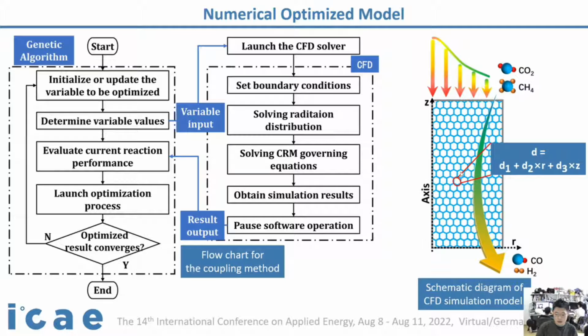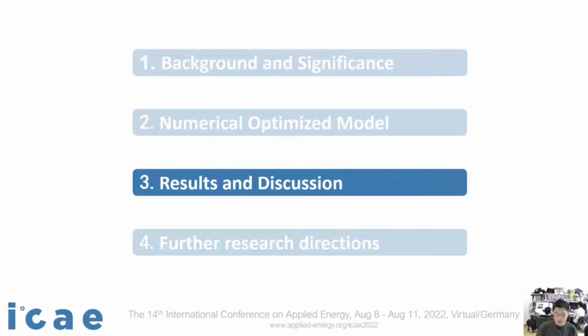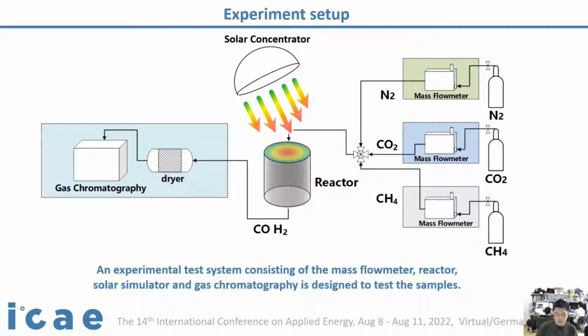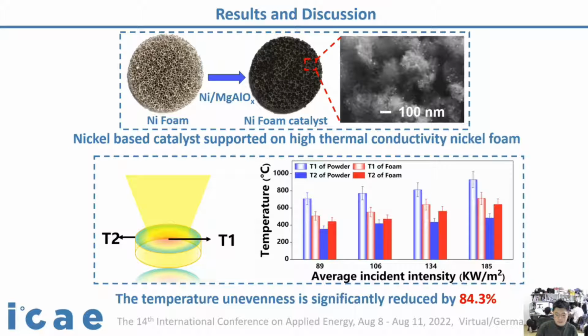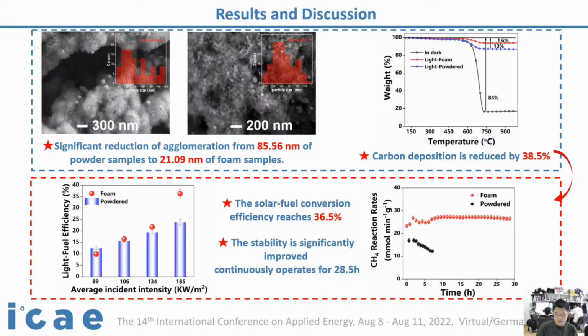The next comes the third part, results and discussion. We first built an experimental test system consisting of the mass flow meter, reactor, solar simulator, and gas chromatography to test the samples. Then we got the nickel-based catalyst supported on the nickel foam. Because of the high thermal conductivity of the foam, the temperature unevenness is significantly reduced by 84.3% compared to the powder sample.